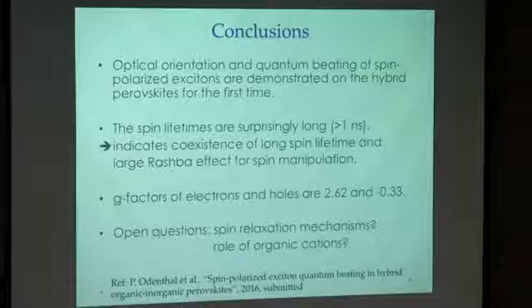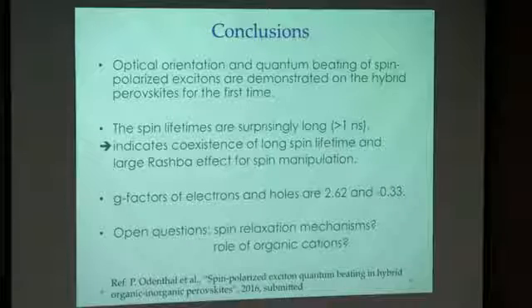Okay, here's my conclusion about this part. We demonstrate optical orientation and the quantum beating of the exciton states in this hybrid perovskite for the first time. And we measure very long spin lifetimes, more than 1 nanosecond. That indicates that we have coexistence of a long spin lifetime and a large Rashba effect for spin manipulation.